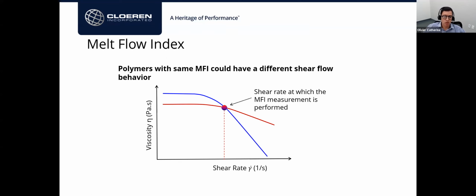And you can see here that I'm representing a polymer that shear thins a lot less in red compared to the blue polymer, which starts off with a much higher zero shear viscosity in this case. If you were to design equipment the same way for the blue and red polymer, you would end up probably in some trouble at some point.